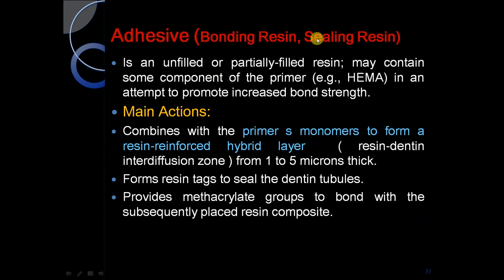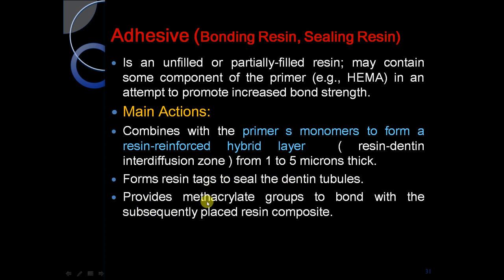The adhesive, or bonding resin or sealing resin, is an unfilled or partially filled resin that may contain some component of the primer, e.g., HEMA. In an attempt to promote increased bond strength, their monomers combine with the primers to form a resin-reinforced hybrid layer ranging from 1 to 5 microns thick. They form resin tags which help seal the dentinal tubules and provide the methacrylate group to bond with subsequently placed resin composites.